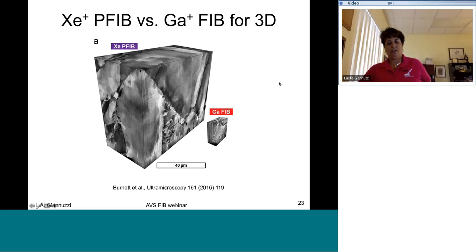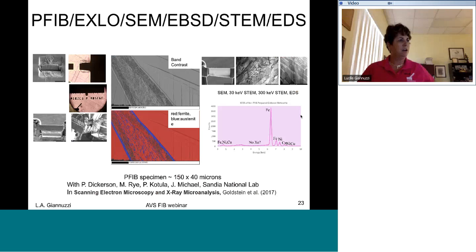So here's an example from the work of Burnett et al. a couple years ago. They were looking at material doing 3D analysis, basically in the same amount of time. This is a xenon plasma FIB versus gallium FIB for 3D analysis, and in the same amount of time, they looked at, I don't know what the factor is in volume, but maybe 1, 2, 3, 4, 5, 6, at least 10 times more or more. So again, you can FIB through larger materials faster using xenon plasma FIB. And yes, you can make TEM samples with the plasma FIB.